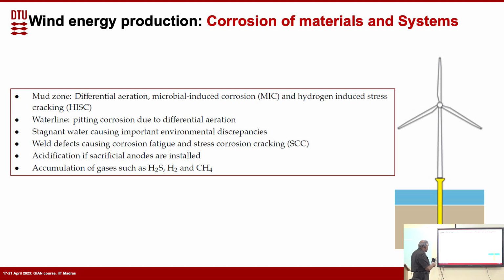And welding corrosion is in many places. Welding corrosion can be there anywhere, because there is a lot of welding in this tower, and all the weld region is more prone to corrosion. Not outside that much, but inside the tower the paint layer thickness will be less compared to the outside. So inside there is much more chance for weld corrosion compared to outside. You will see later that they put a very, very thick coating outside to reduce the corrosion problem.